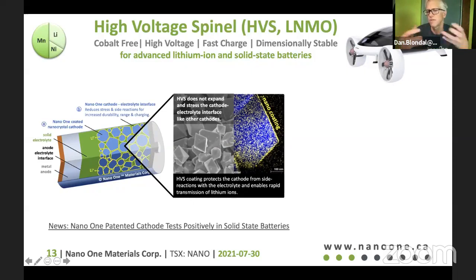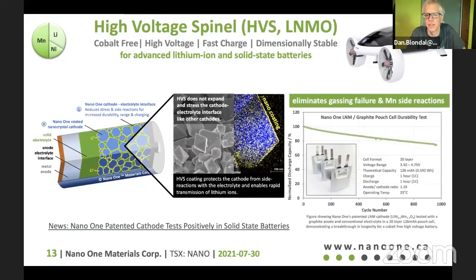Before everything goes into the furnace, our coating material is already mixed uniformly with all the other chemicals. It's only when you heat it up in the furnace and everything starts to form the right crystals that the coating material is actually pushed to the outside of every little crystal to form that little yellow skin that you see on the outside, and it makes for a very uniform and effective protective coating. One of the things that's allowed us to do is take this high voltage material and run it in a high voltage battery. Typically, high voltage batteries fail within a couple cycles.